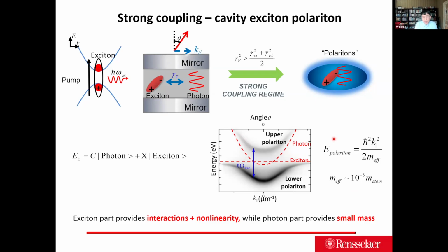So in this case, the exciton part provides interaction and nonlinearity, where you can effectively pump the system and generate a lot of particle density, while the photon part provides small effective mass. In this way, the polariton inherits both the good aspects of the exciton and the photon, where you can see a lot of this high temperature behavior with the Bose-Einstein condensate, which is actually what we are hoping for.